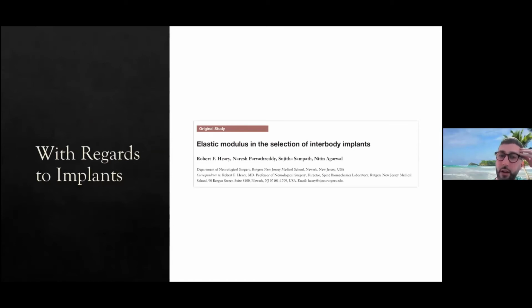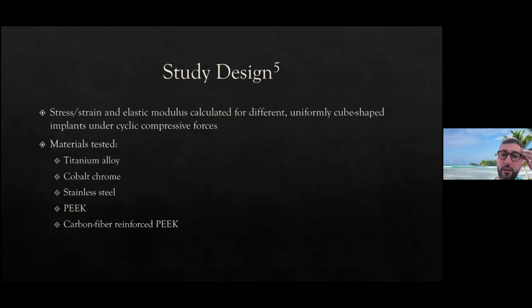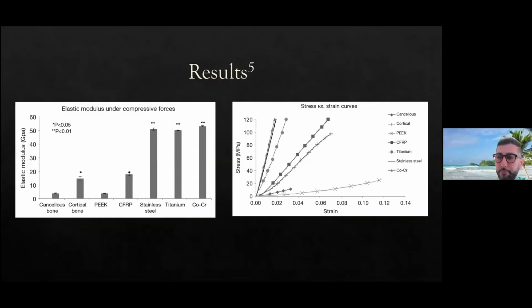So this is a study that's talking about modulus of elasticity in the selection of interbody implants. And basically, they have these multiple uniformly cube-shaped implants made of titanium, titanium alloy, cobalt chrome, stainless steel, PEEK, and carbon fiber reinforced PEEK. And they test them under cyclic compressive forces. And these are basically the results. And the overarching point of what the study's talking about, which is what you can see here, is that all of the metals, whether it's stainless steel, titanium, or cobalt chrome, have a very, very different elastic modulus than either cortical or cancellous bone, which you see all the way to the left here in these graphs.